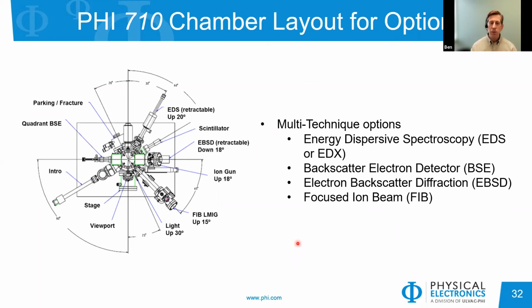So we have EDS, which is going to give you more of a bulk elemental information than Auger. So those actually can work very nicely together, complementary. And there's also backscatter electron, EBSD, so we can get more crystallographic information. We also have a FIB. So if you do want to do cross-sectioning and then look at interfaces, we can do that as well on the system.